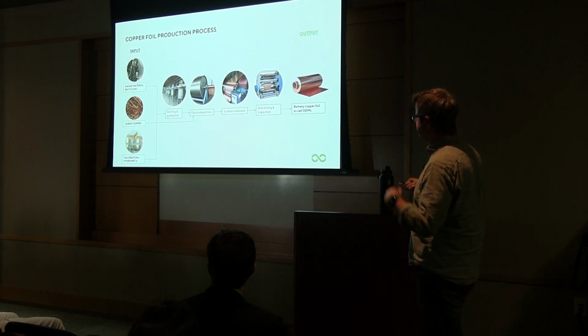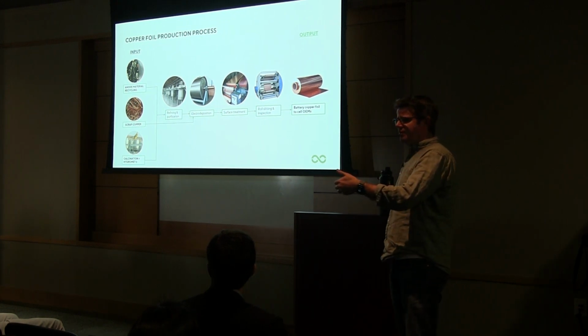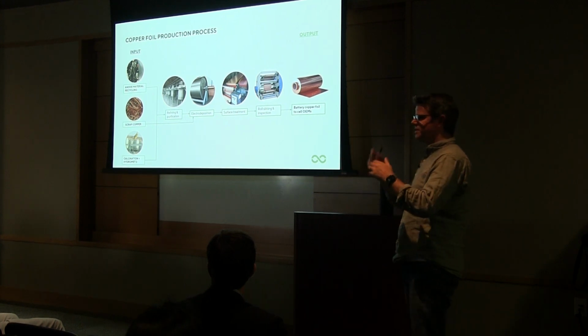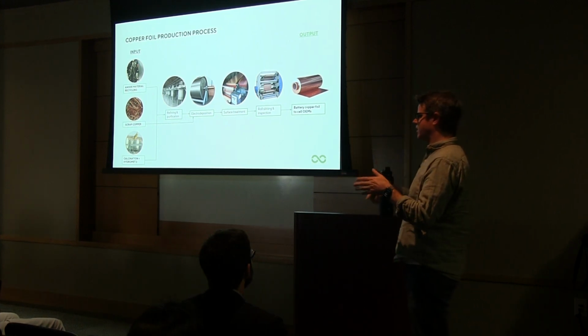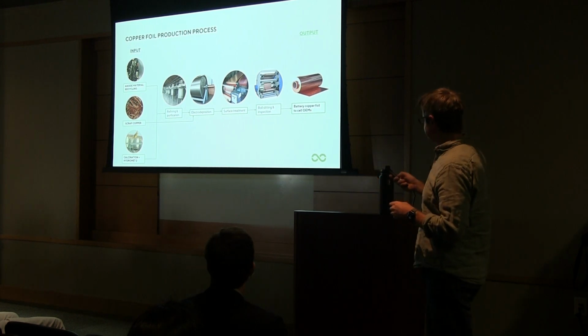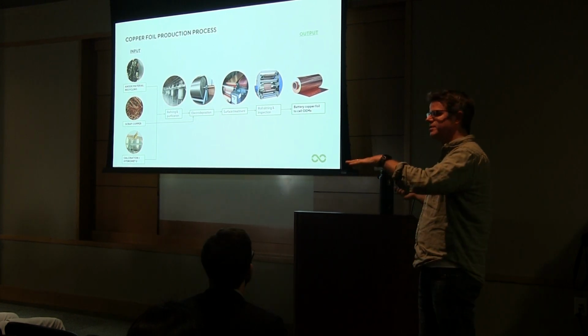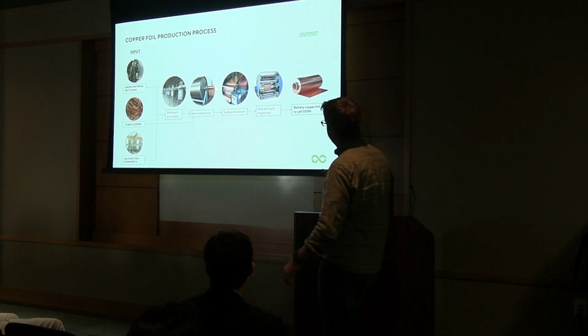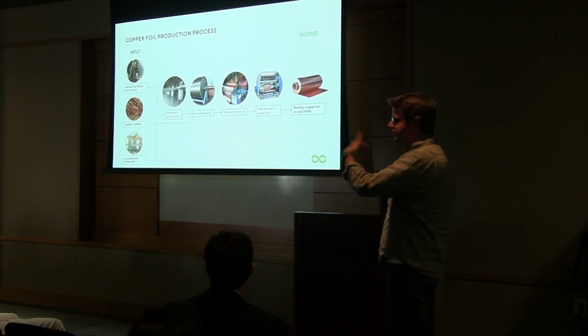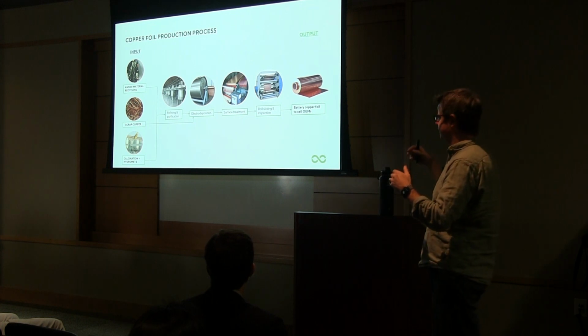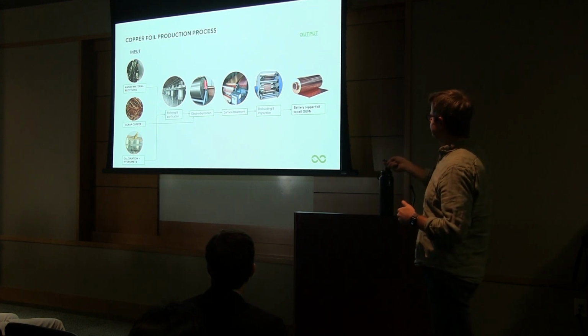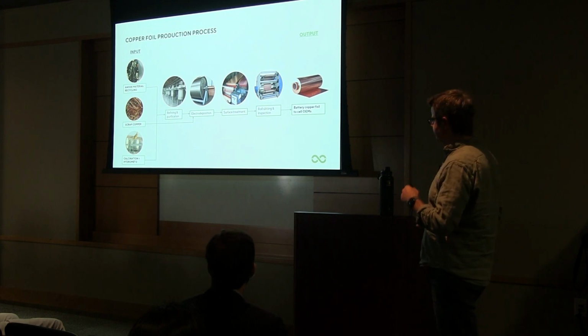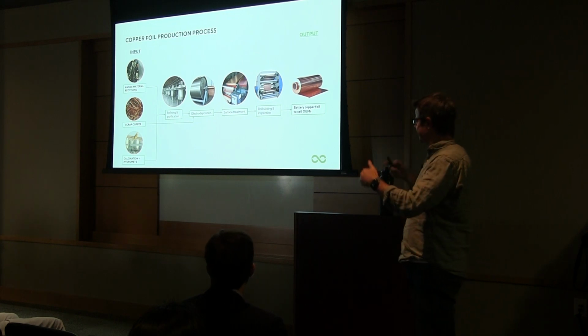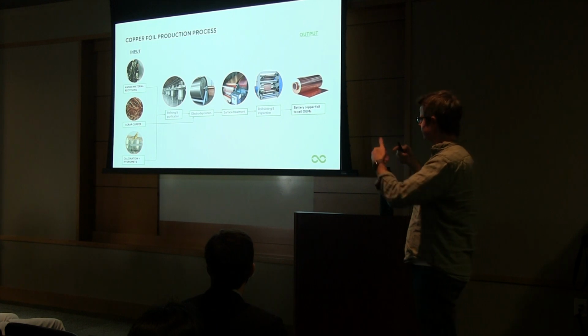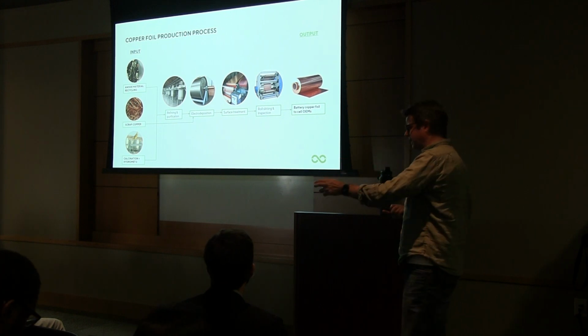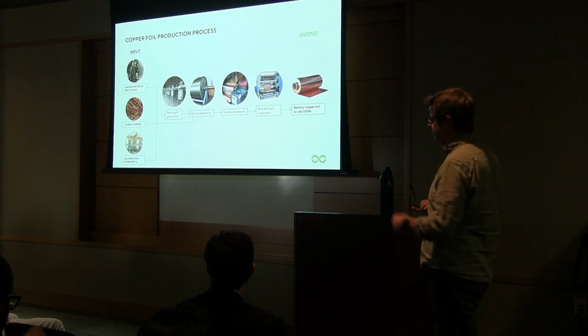The first thing that we do is we dissolve the copper through a continuous dissolving system. So there's a circulating electrolyte loop, which is about 100 grams per litre copper, 100 grams per litre acid. It's basically a copper sulfate solution flowing past this big rotating drum. That drum's continually rotating, and there's a current passing through it. And basically, this drum is the cathode. The anode's on the other side of the bath. And what we're doing is continually plating to remove copper out of solution, generating a small amount of acid. That acid goes back and dissolves more copper.